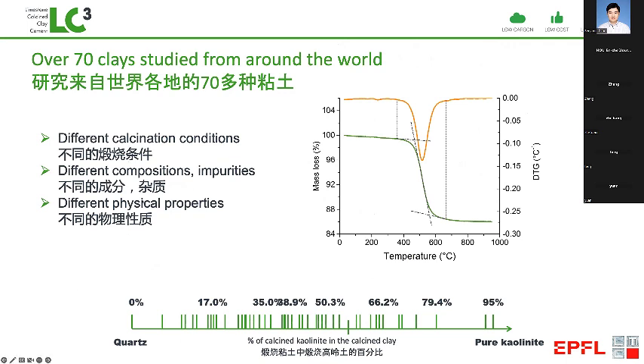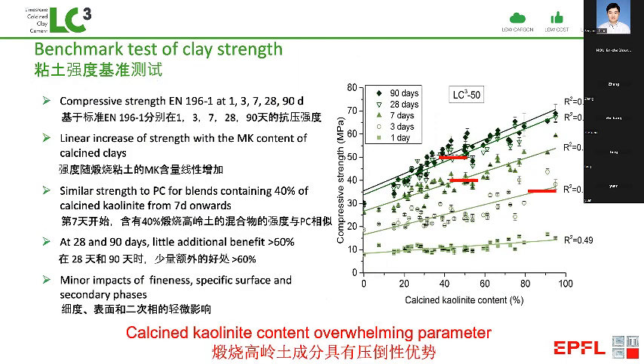We can measure the kaolin content quite easily by looking at this weight loss step in the range 400 to 600 degrees. And when we look at the strength development, we can see that this kaolin content is the overwhelming parameter controlling strength.